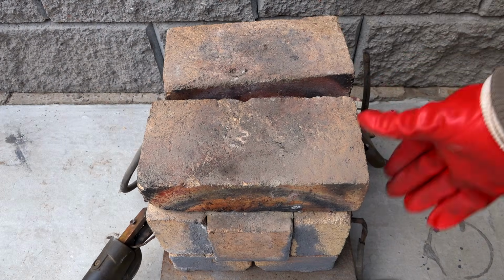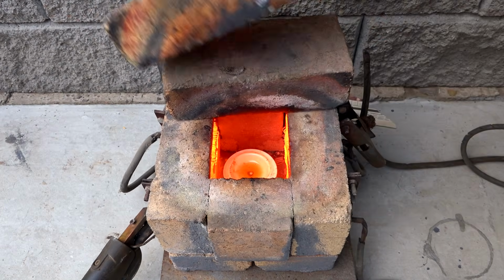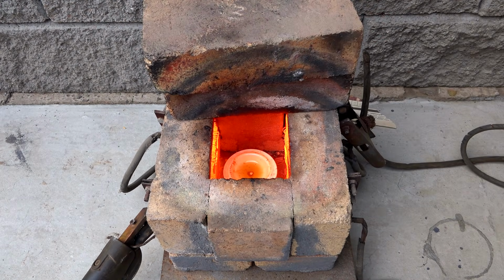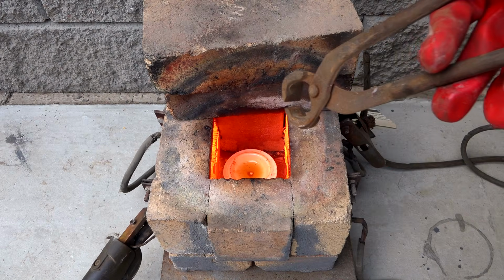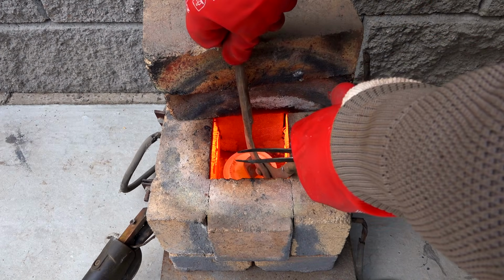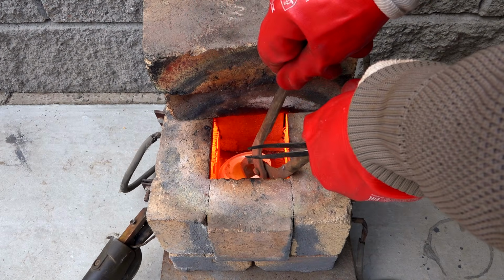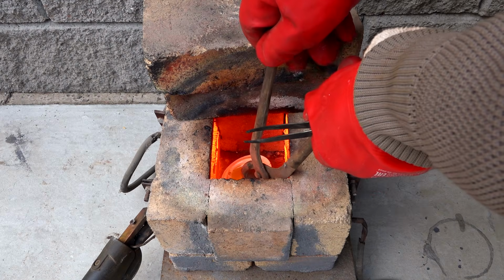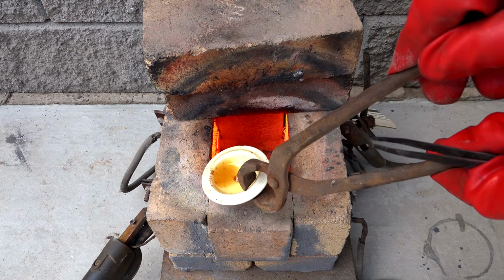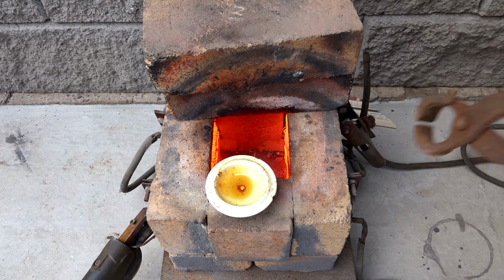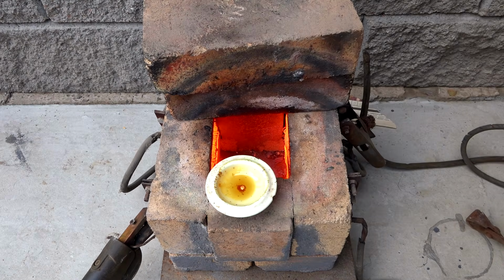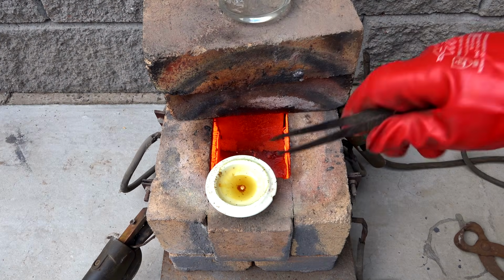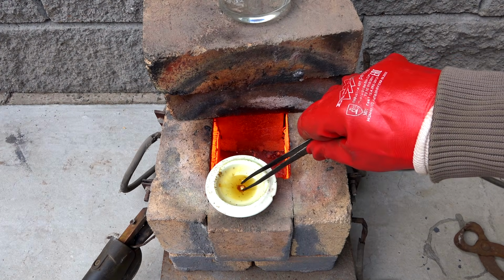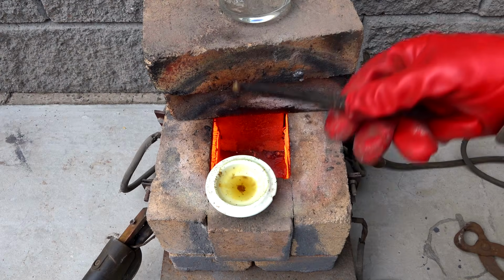After another 20 minutes, the muffle furnace reached the desired temperature, and the gold precipitate melted neatly into a ball. After a few minutes, I reduced the heat to let the gold cool slightly, and the ingot easily emerged from the glassy borax. In my opinion, everything worked perfectly, the crucible didn't crack. This means I'll be melting gold in it regularly from now on, and I got it for free.